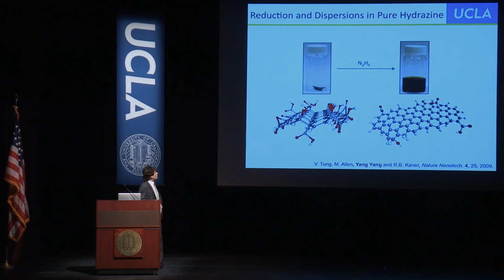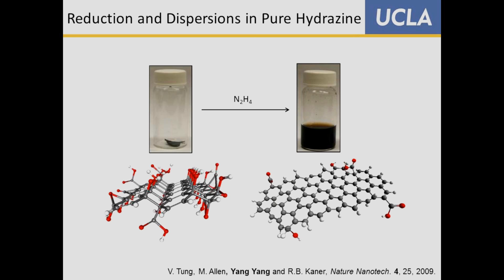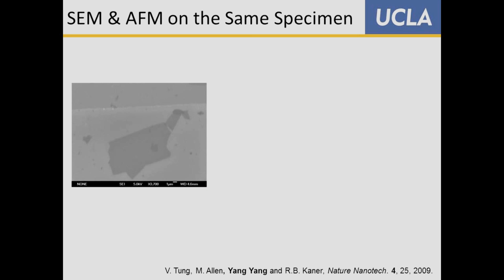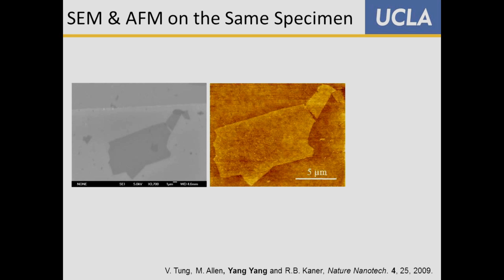We even tried reducing this in pure hydrazine to make an even better colloid and a better material. And this is work done with Yang in material science. And when we did this, at the time we produced the largest sheets of graphene that had been made. And this is a scanning electron microscope picture of a very large sheet of graphene. And here's an atomic force microscope picture. And I think if you stare at these for a moment, you'll agree that these are the same picture. So about 20 by 30 microns.